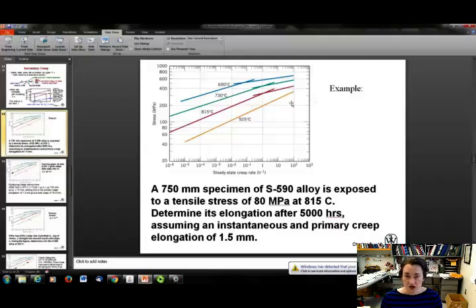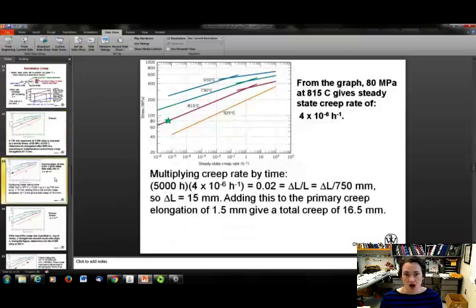So these curves here show the secondary creep behavior, and the instantaneous and primary creep elongation are given to you basically as 1.5 millimeters. So you just need to figure out the secondary part and add it onto the primary. All right, so what we can do is we know that the part was subjected to 80 megapascals at 815 C. So I can look at my plot here and read off for 80 megapascals from the 815 C curve, which is that red curve here, and see what the creep rate is at that value. So reading that off the plot, I get 4 times 10 to the minus 6 inverse hours. Again, the units are a little strange on these things. Just go with it. Okay, so here's my steady state creep rate.